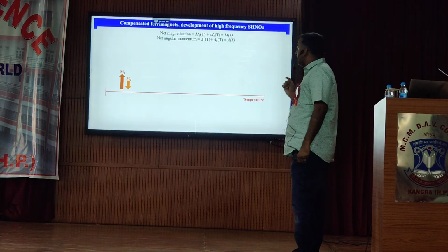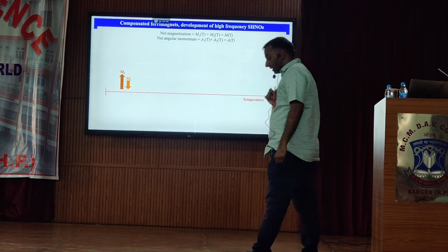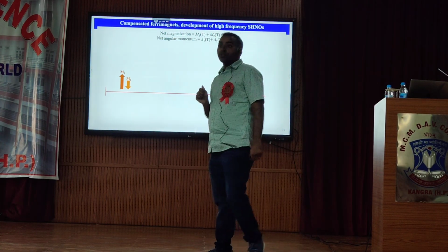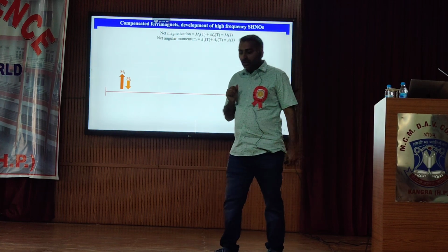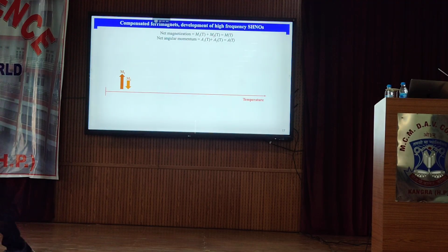And that net magnetization value, which remains in compensated ferrimagnets, gives us an advantage over antiferromagnets. For the last 10 years, antiferromagnets have been very interesting to researchers working on ultrafast dynamics devices. But there is a challenge in antiferromagnets. As I said, the net magnetization is 0, so it is very difficult to measure the signal.